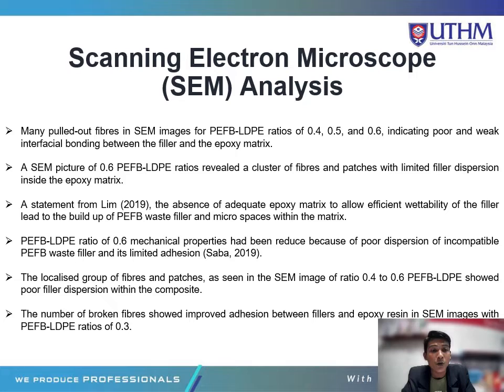PEFB ratio 0.6 mechanical properties have been reduced because of poor dispersion of the incompatible PEFB waste filler and its limited adhesion, according to Saba, 2019. The localized groups of fiber and patches seen in the SEM images of ratios 0.4 to 0.6 show poor filler dispersion within the composite. The number of broken fibers showed improved adhesion between filler and epoxy resin in the SEM image of PEFB LDPE ratio 0.3.